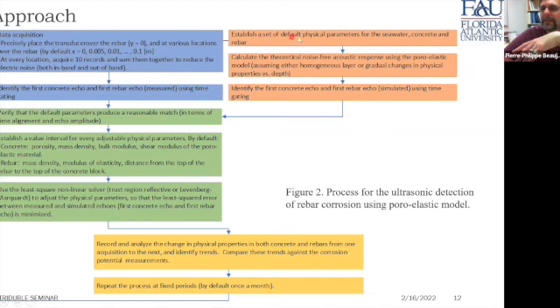At the same time, we establish a set of default physical parameters for the seawater, concrete, and rebar, and we calculate the theoretical noise-free acoustic response using the Poro-Elastic model, assuming either a homogeneous layer or gradual changes in the physical properties versus depth. Now, I would like to mention that the assumption that we have a noise-free environment is a reasonable assumption, as the transducer itself is very quiet. The acquisition system itself is very quiet. And we work in an environment where there are very, very few vibrations. So the signal tends to contain relatively little external noise or electrical noise.